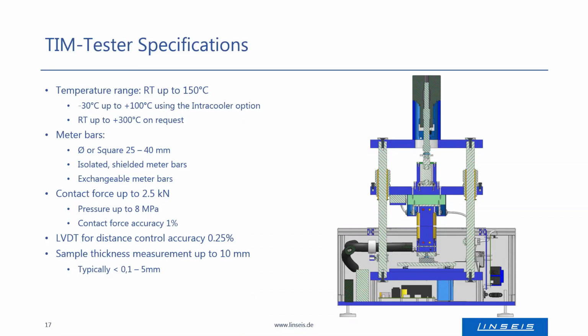The standard meter bars which are used are out of aluminium, and with that one can, for example, measure a thermal conductivity range of 0.1 to 50 watt per meter Kelvin.